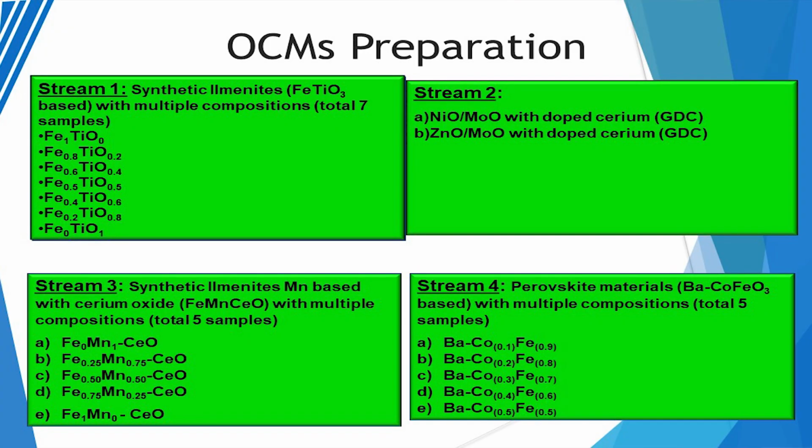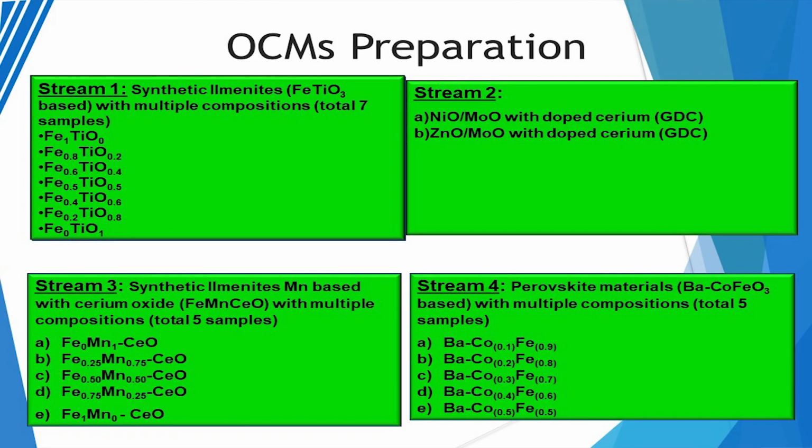Here we used one material which has a 50% ratio of iron and titanium. Titanium can also stabilize the iron phase. First we checked in fuel syngas, and then in methane. Methane is very stable, but the oxygen transfer capacity in syngas is very good, because in methane there is some carbon deposition on the material, and then some agglomeration during this process.